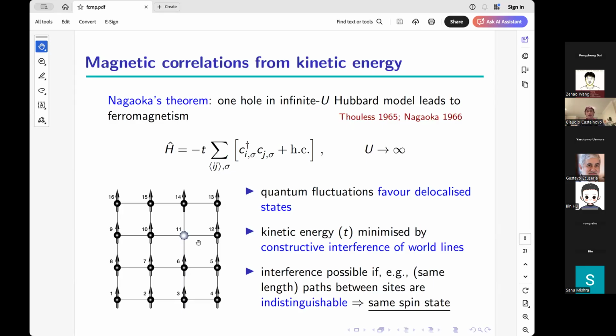And this means that this lowest energy state is achieved by allowing perfect constructive interference whenever the hole hops from one side, travels from one side to another along different paths of the same length. And this is achieved on a square lattice if the spins are all the same. If the background spins are different, when you move along 2 different paths, you generate a different configuration and interference cannot happen. As a result, quantum mechanics cannot take advantage of interference to minimize the energy, does not generate a superposition, and the state costs more energy than a ferromagnetic one.